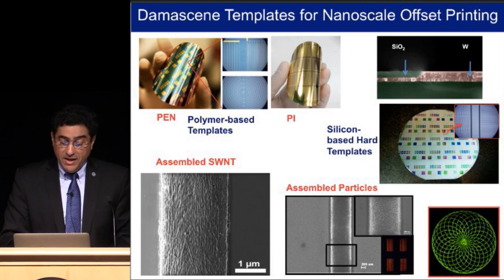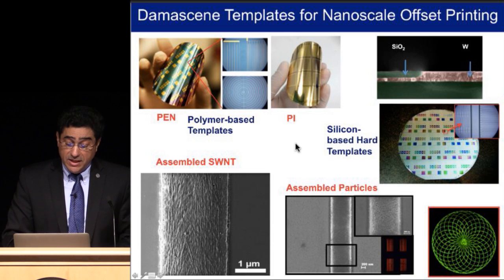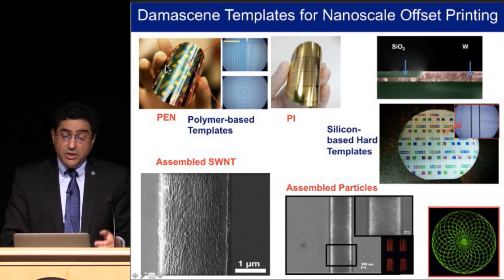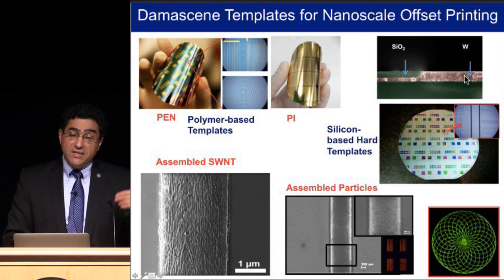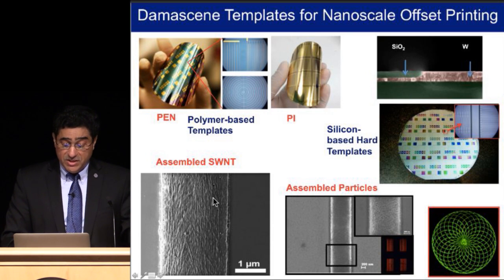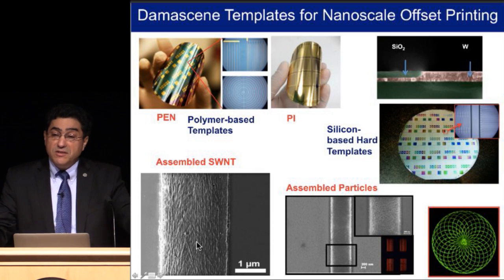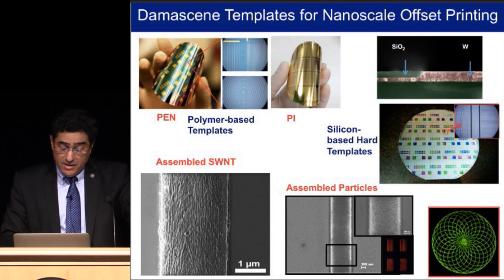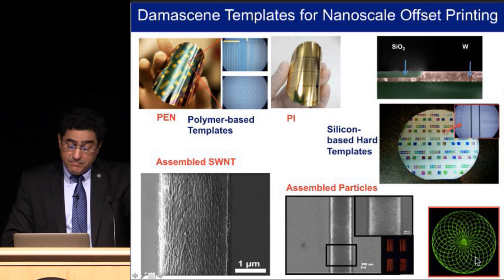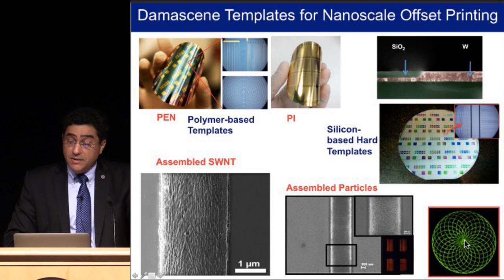There are two of them. And this is the hard template. So silicon, tungsten, the conducting wires are tungsten. And this shows examples of the assembly before it's transferred from the template to the substrate. These are fluorescent silica particles, green fluorescent, to see them. These are silica fluorescent particles. These are silica red fluorescent particles.